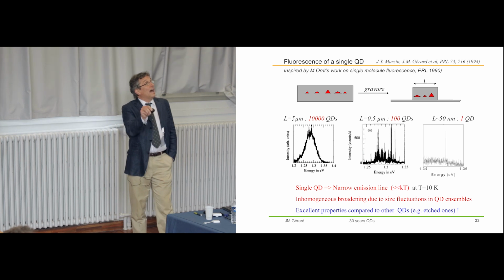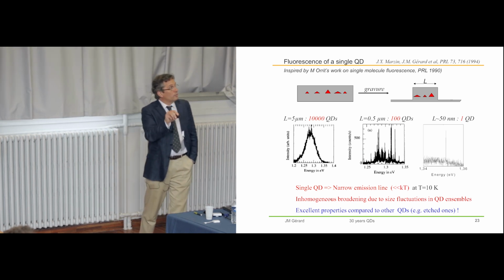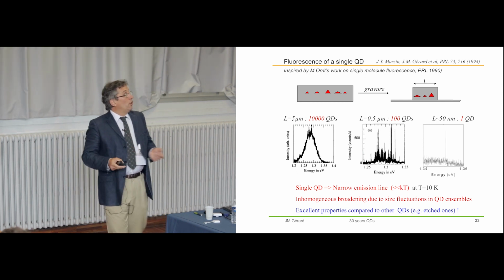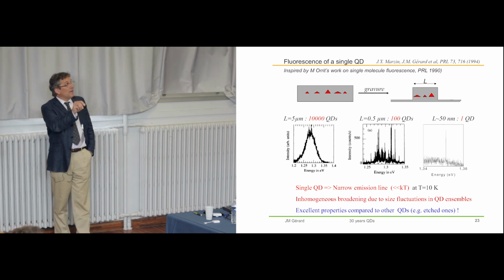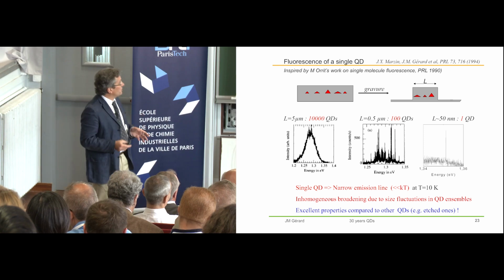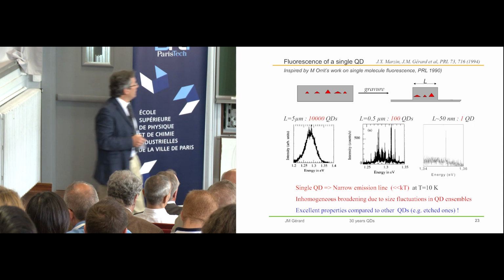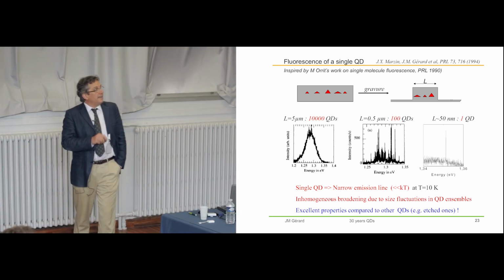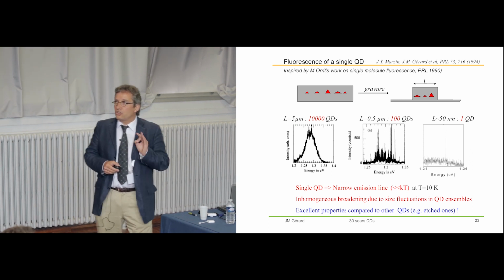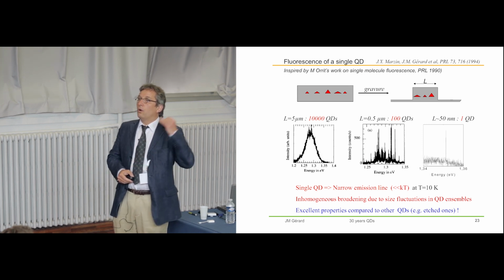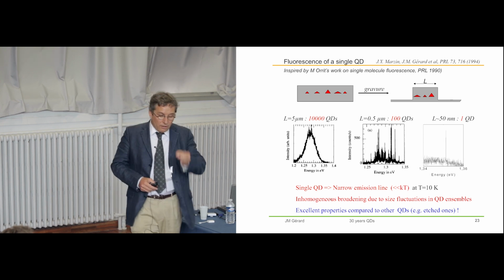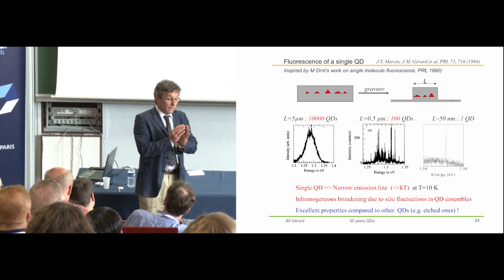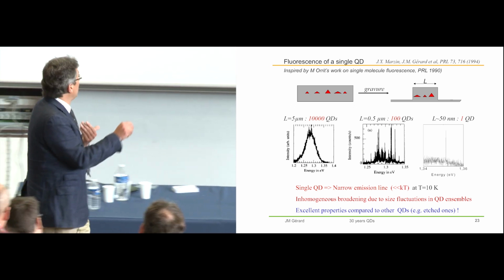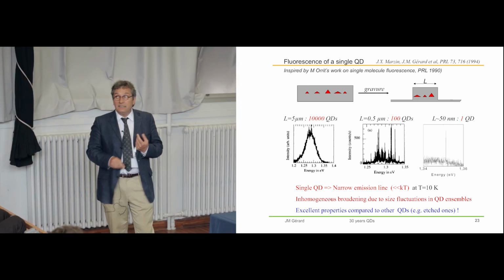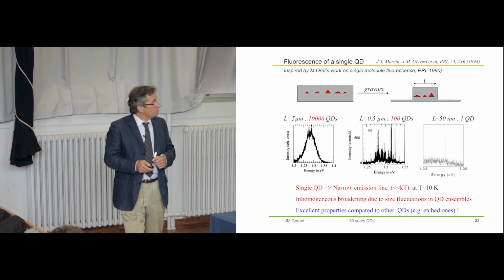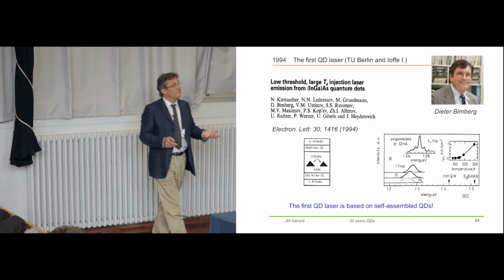So this tells you a lot. At low temperature, here the experiment was done at 10 K, quantum dots exhibit sharp lines as expected for artificial atoms, let's say. And also, the inhomogeneous broadening due to size fluctuation is responsible for the broad emission line in quantum dot ensembles. Here again, this experiment demonstrated that such dots are far superior to dots obtained by other approaches. When a single dot defined by etching was studied, the emission lines were always rather broad. So it was the first time that a quantum dot exhibited an emission line much narrower than kT. So nature gives you the best dots, the most intrinsic ones.